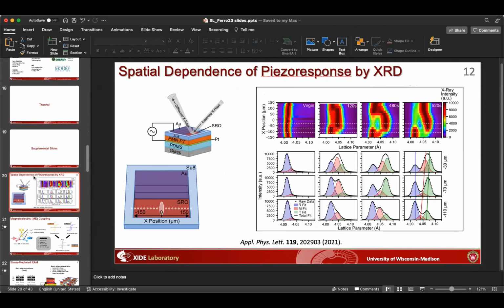But as we cycled this voltage, what we're showing is at 0 volts, all the X-ray data is taken. But after various time steps of AC cycling, we could nucleate and grow these tetragonal domains. And then because of the self-clamping effect along the edges, it wants to stay more rhombohedral. In the middle, it becomes tetragonal, but certainly not the cleanest in terms of domain structure.